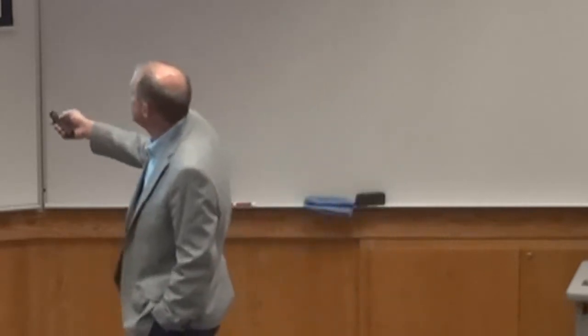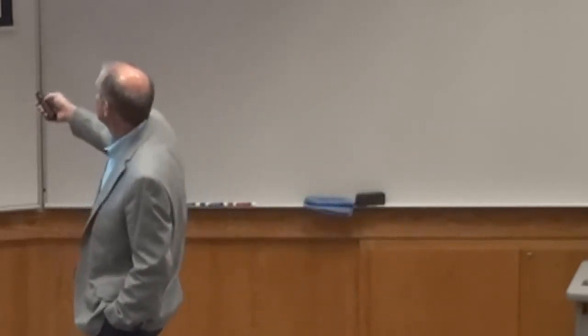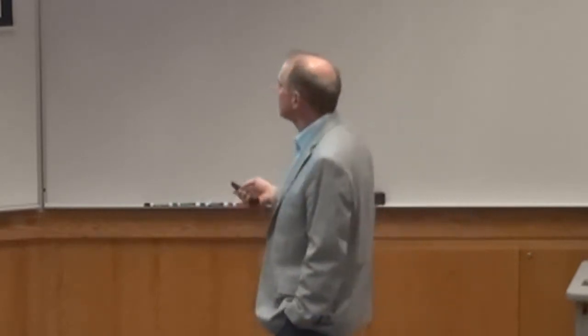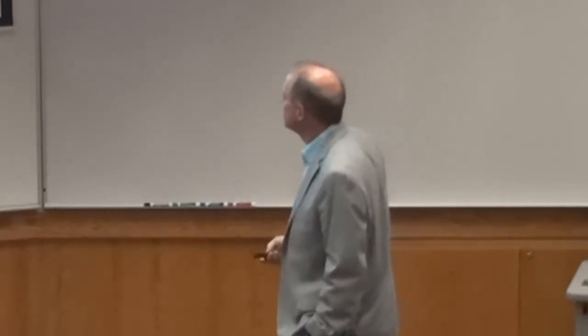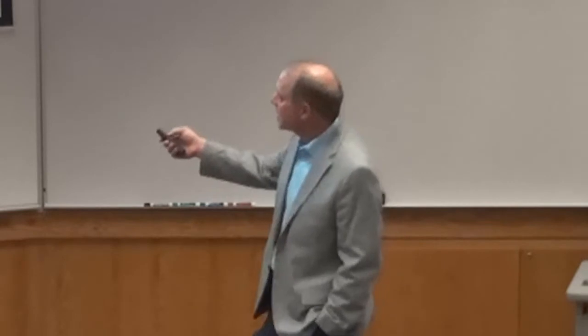And so you can do laser ultrasound in the time domain. And that's what I have here. So this is generating here, and this is detecting on the other side. The first thing you see come through, the first disturbance, is the longitudinal wave, and the second disturbance is the shear wave. And some easy things you can do with this is, from these two measurements, you can calculate both elastic constants if it's an isotropic material. So that's the time domain.